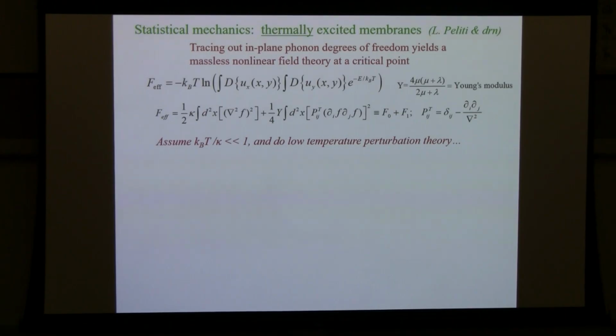Okay, so what do we do at finite temperatures? It's already hard at zero temperature to solve these problems. Well, if you go back to that original model of stretching and bending energies, it's nonlinear to be sure, but the in-plane phonons only occur quadratically. And so what you can do is trace them out. And that produces this interesting massless field theory. So kappa is the bending rigidity, and here's a soft restoring force, Laplacian f squared. And now the Young's modulus comes out in front of this strange-looking transverse projection operator acting on the tilts. These are gradients of f, so you can think of them as little tilts of Heisenberg spins. And so what that does is produce an interesting interaction between these Heisenberg spins.